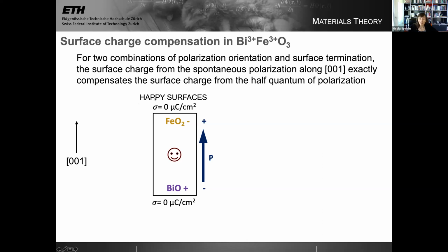This is a really happy, electrostatically completely content surface, right? There's no net surface charge, there's no diverging electrostatic potential. I can make a very, very thin film of bismuth ferrite, provided I choose this combination of surfaces and this orientation of polarization, and it's electrostatically stable. So this is completely remarkable. It's very, very difficult to make a thin film of a ferroelectric and not have it want to explode. And in bismuth ferrite, it happens spontaneously because of this unusual cancellation.